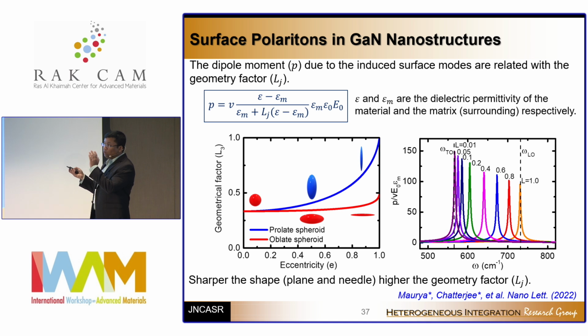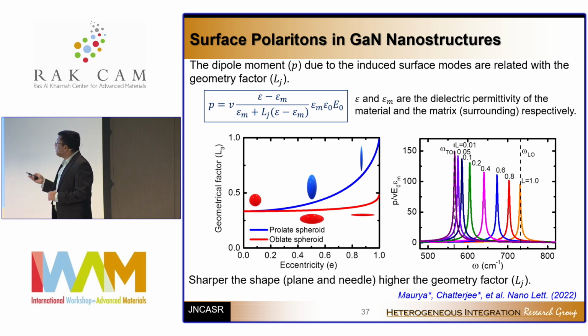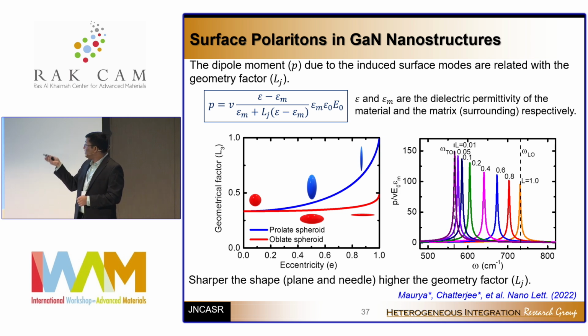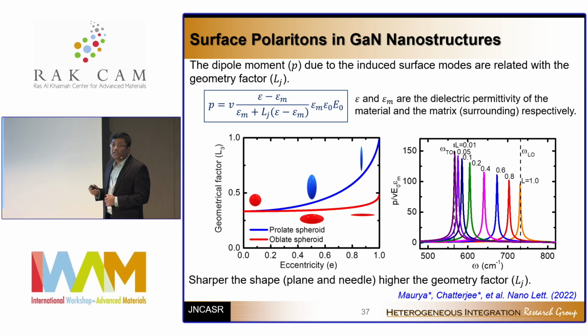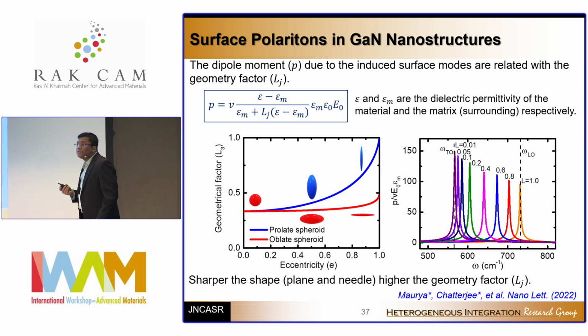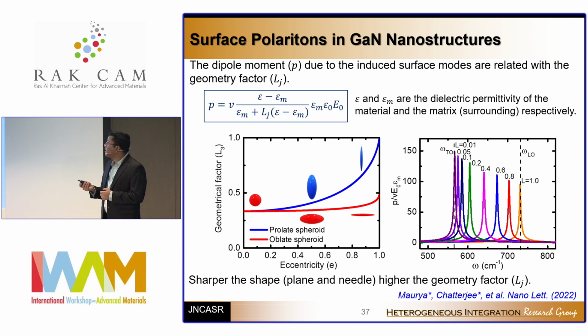Now, given that our nanowires are vertical, these absorption resonances occur close to the LO phonon frequency, and because of this absorption, you see the reflection pretty much going down and giving you a trapezoidal shape. So the nanostructuring basically offers you a new possibility to engineer the optical properties of gallium nitride nanostructures, which are pretty much industry used. So if you want to achieve some application, you can do it without much changing the growth process or fabrication techniques.